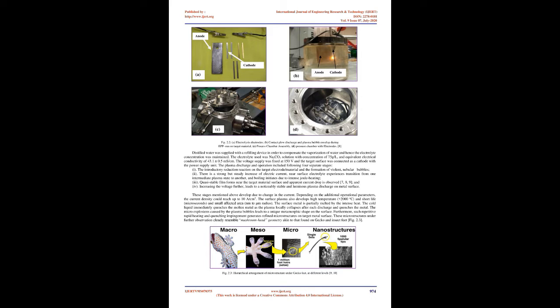IIB. Preparation of target materials and plasma bombardment. The commercial AISI 1018 low-carbon steel was used in this study, wt% 0.18 C, 0.6 Mn, 0.05 S, and Fe balance, for electrolytic plasma processing 7, 8. Samples were first mirror polished with emery paper to a grit level of 2400, then ultrasonic cleaning was conducted in ethanol for improving the surface finish. Scanning electron microscopy, SEM, and energy dispersive X-ray spectroscopy, EDAX, were performed on the sample surfaces.